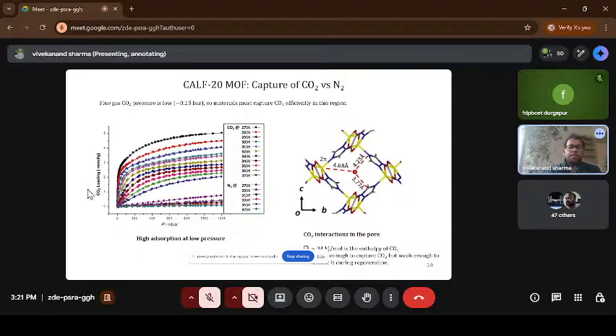From this graph, the bottom part represents the nitrogen capture, and this large curve, which is bending like this one, is for the CO2. At lower pressure, like 200, 400 millibar, we can see the nitrogen uptake is very little. It means that the material is not capturing the nitrogen at all. But at the same lower pressure, you can see a very high uptake of carbon dioxide gas compared to the nitrogen.